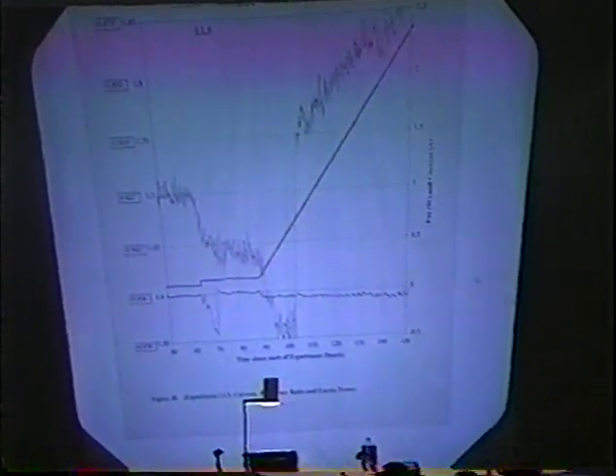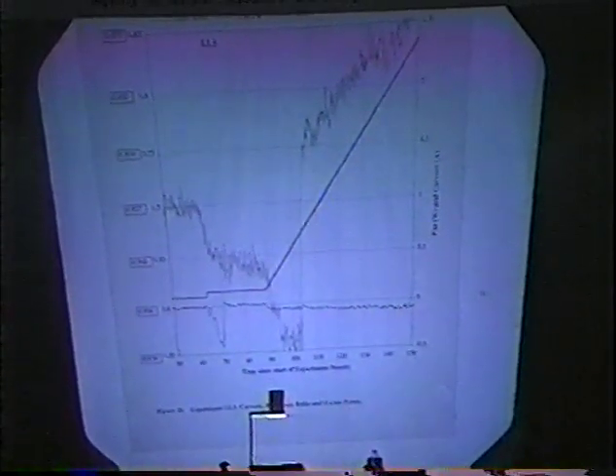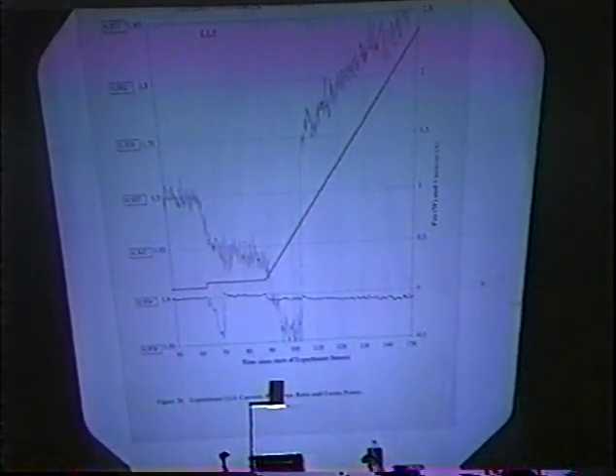To explain such an explosive deloading process, you need a mechanism with positive feedback, and I suppose that at a certain point one part of the cathode becomes incapable of maintaining that high activity, bubbles start to form, and you get a mechanical disruption of the film that was otherwise doing good things for you. So now the film is essentially blown off the entire surface and the cathode deloads. So I think there are mechanical effects due to the bubbles which contribute to our failure. It doesn't explain why we were successful in the past though, with cathodes that are able to maintain the loading at high current densities. What's the difference in that case?